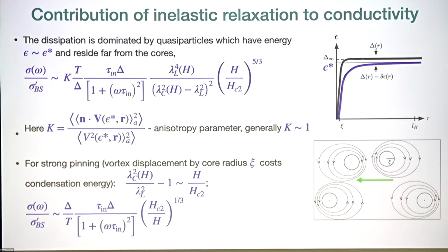In general, it's of order 1 with strong pinning. And then there's magnetic field dependence, which is hidden inside these two factors. Well, this is complicated, but if you assume very strong pinning, if you estimate the pinning constant by saying that when you displace a vortex by a distance of order of the core radius, you change the energy of the core by essentially the condensation energy, then you get a much simpler expression, the dependence on H is a simple power law, and then factors.